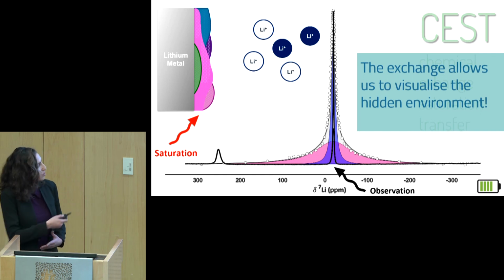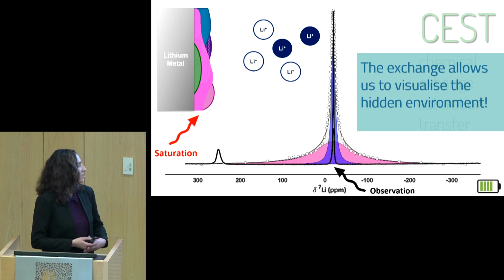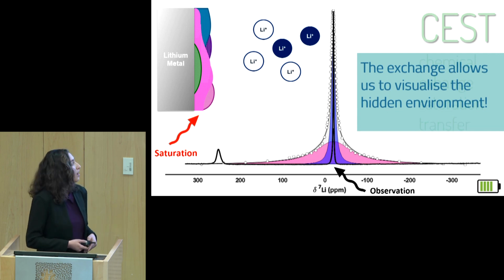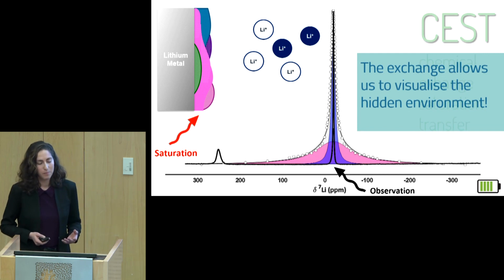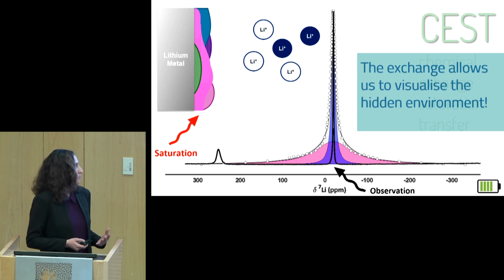We see it here in this measurement in the pink region, representing the surface-bound lithium, and the blue peak representing the original peak of the dissolved lithium ion. The pink peak is very broad because the surface is actually composed of many different chemical environments. So it's not just at one frequency.